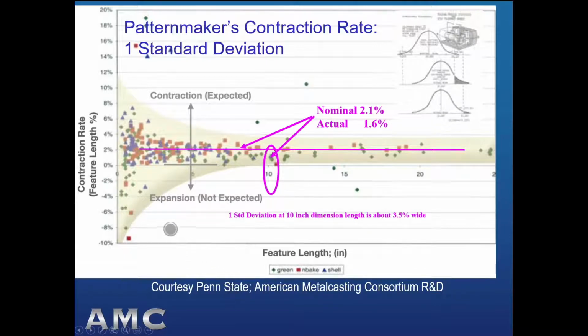And what we see here is the contraction rate based on feature length on the x-axis, and just look at the variation from contraction, which we expect, to some expansion, which we wouldn't expect, but the overall nominal rate is 2.1% for carbon and low alloy steels, which is what these experiments were conducted for. But in this case, we actually got 1.6%.